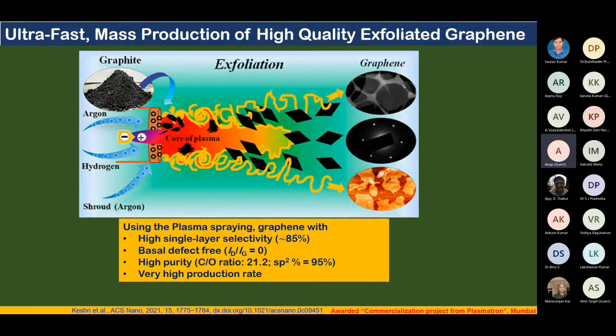Basal defect free, that is, the basal plane had no defects at all. That is why we are talking about an ID by IG ratio of 0. It had high purity, with a carbon by oxygen ratio of 21.2 and sp2 content of around 95%. If we look at the carbon by oxygen ratio, it is comparable with the CVD technique, which we have already reported in our work.